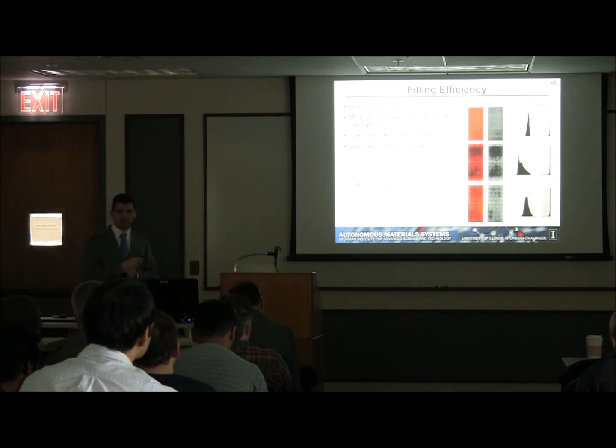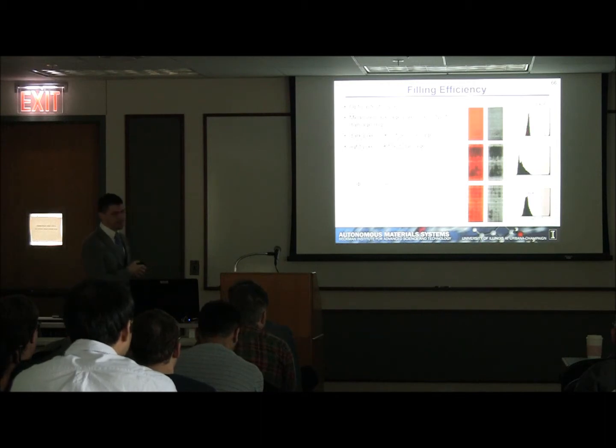We can visually quantify the amount of damage fill using what we call filling efficiency. This is an optical technique using the images from the filling of the samples during the healing process. So if we compare undamaged, damaged, and healed specimens, convert them to grayscale as shown here, and look at the average pixel intensities of each one of these images, we can come up with a value of average pixel intensity for each one of these. Then we come up with a metric of fill efficiency, which is simply ratios of these particular values, which measures on a scale of 0 to 1 how much damage has been filled based on this optical technique.